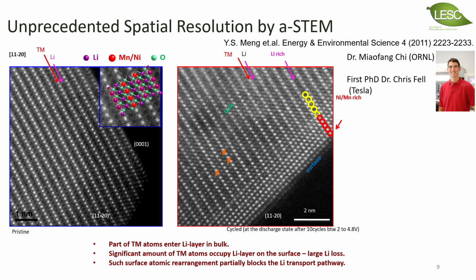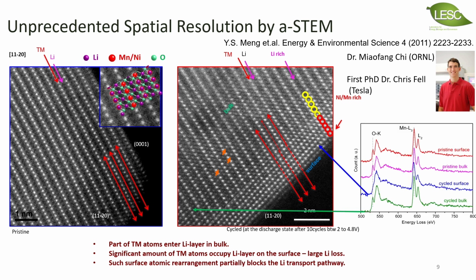After you expose the materials to very high voltage, significant changes happen. And the one thing you see is that this superhighway for the lithium becomes lightened up by those transition metals. And this is one of the first pieces of evidence to show that the major degradation mechanism in batteries is caused by an extremely surface-sensitive mechanism where you have oxygen loss. You see in the EELS, electron energy loss spectroscopy, the oxygen K edge pre-peak disappears, and because the oxygen vacancy was generated, the transition metal starts to move.